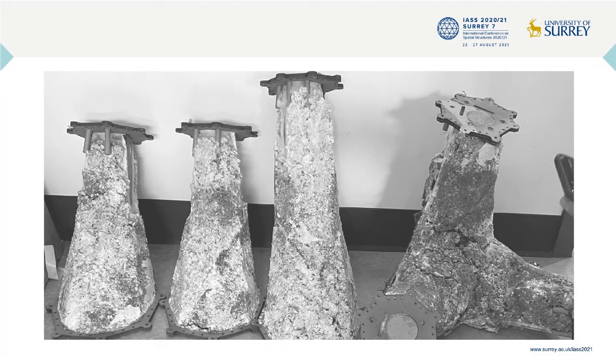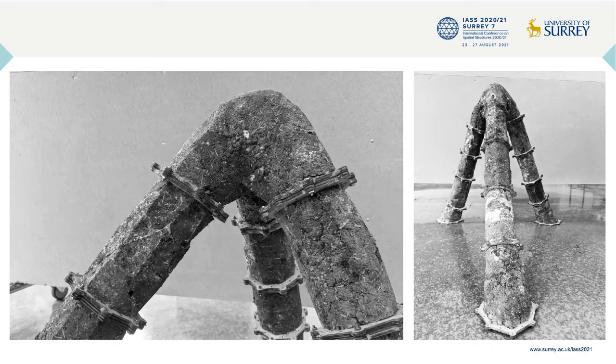We experimented with different sizes, details, and connections for the elements and various cultivation and formwork filling protocols for the materials to avoid contamination. In order to make the material workable, we implemented a series of tests with different bio-based additives such as psyllium husk and guar. We made 4 different prototypes before the final outcome. Here you can see one of the smaller scale prototypes that we fabricated with 13 components.